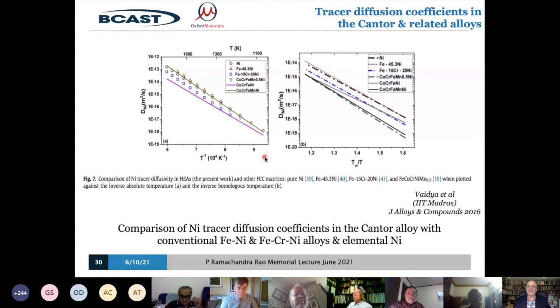We normally measure the speed of motion of atoms by the diffusion coefficient, and we usually plot it against inverse temperature, normalized appropriately. And you can see here that the three Cantor alloys at the bottom have the lowest diffusion, by about a half to an order of magnitude lower than some other comparable kinds of materials. So the rate of motion of atoms is much slower. This means that they're resistant to degradation at high temperature. It means they're resistant to degradation by corrosion, and it means that they're resistant to degradation under radiation, irradiation.